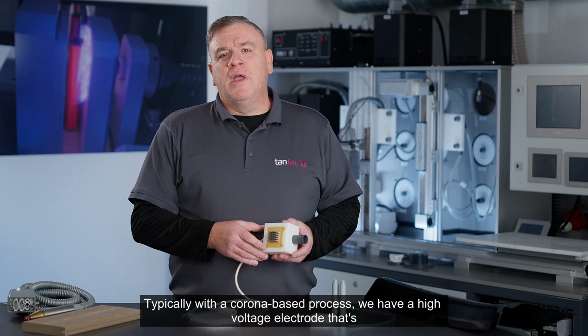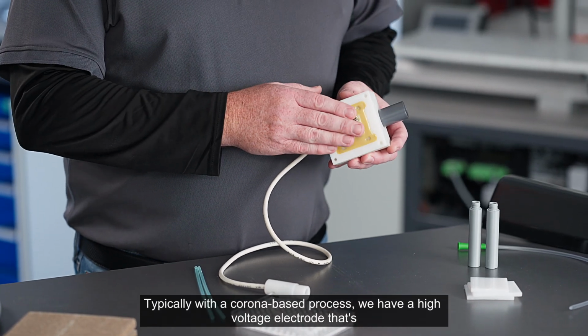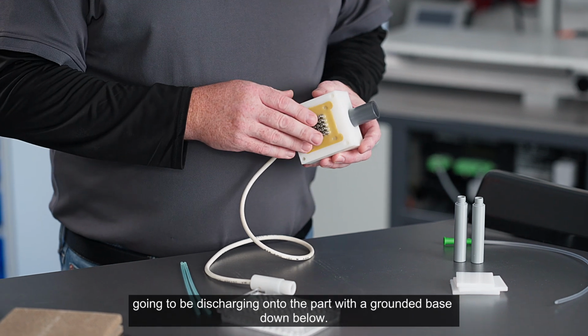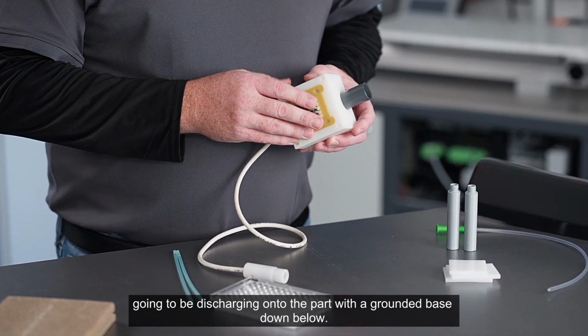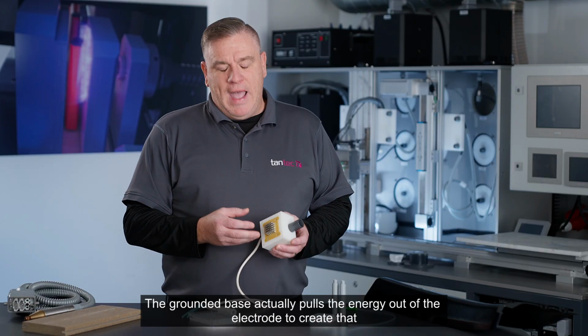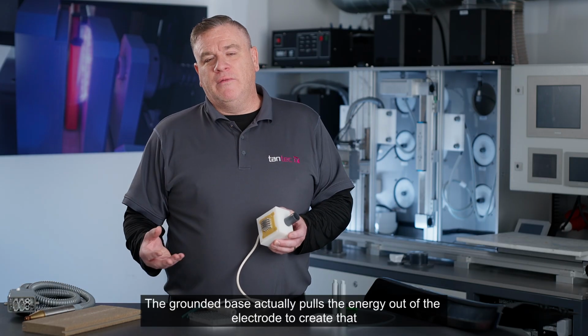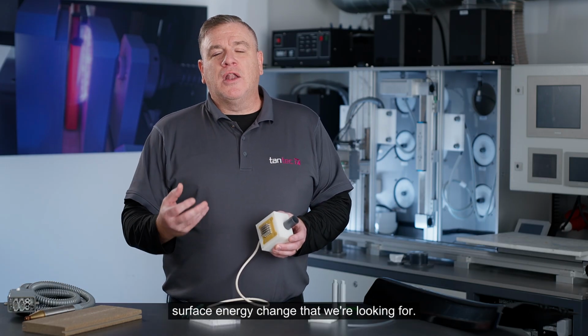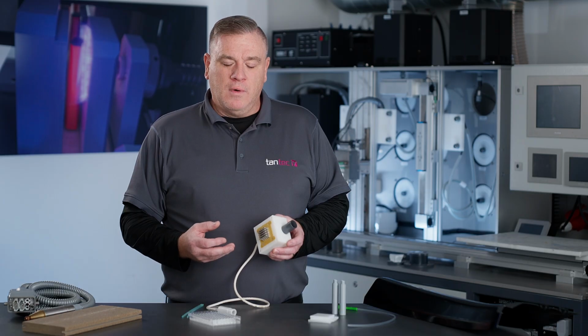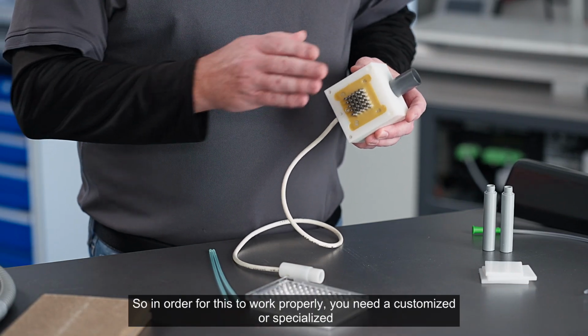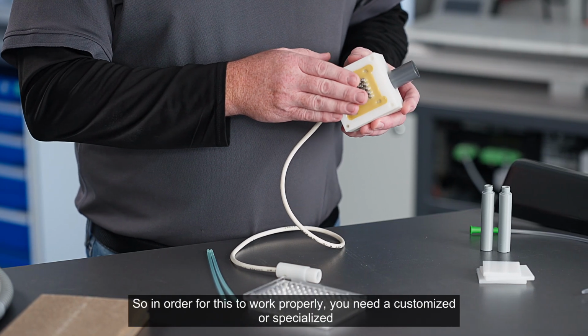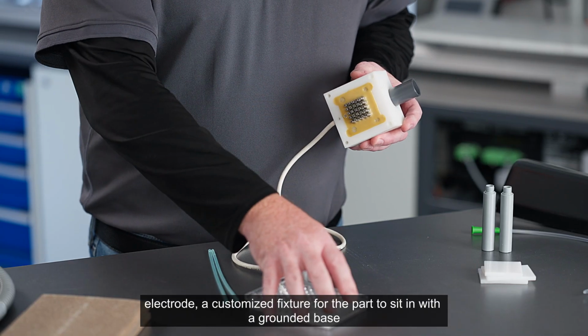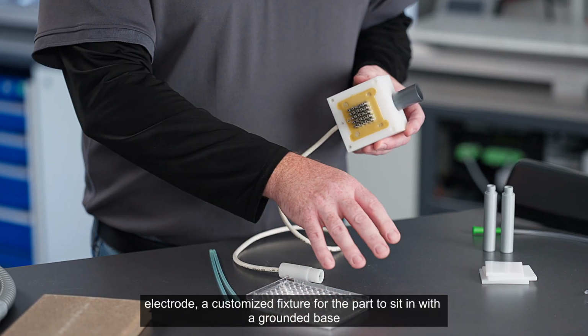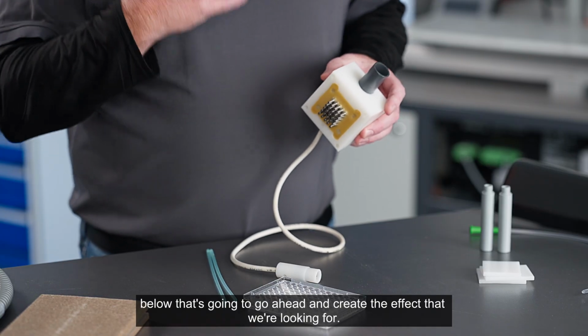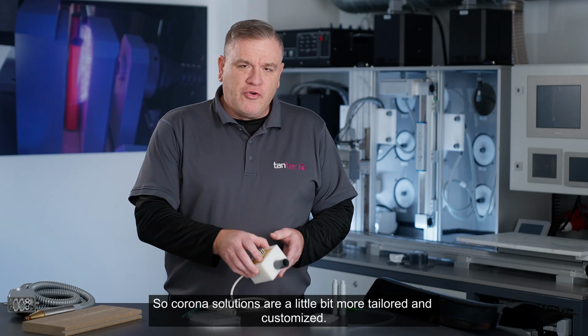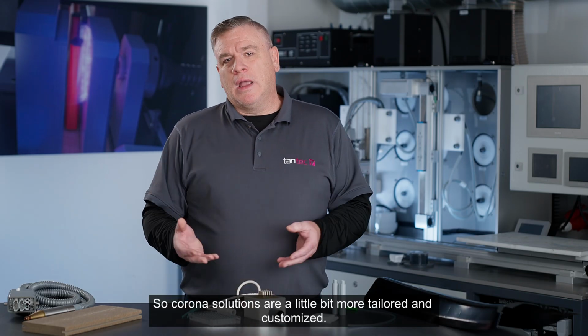Typically with a corona-based process, we have a high voltage electrode that's going to be discharging onto the part with a grounded base down below. The grounded base actually pulls the energy out of the electrode to create that surface energy change that we're looking for. So in order for this to work properly, you need a customized or specialized electrode, a customized fixture for the part to sit in with a grounded base below that's going to create the effect that we're looking for. So corona solutions are a little bit more tailored and customized.